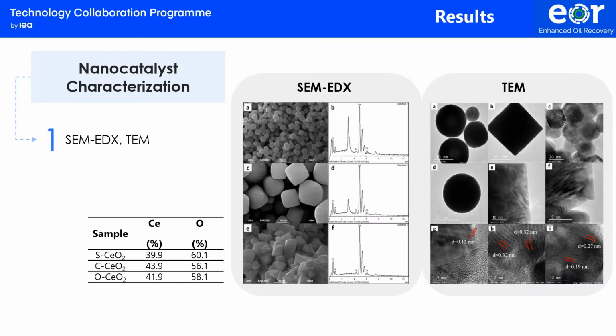As for the characterization of the nanoparticles, morphology and size were validated. The diameter of the spherical nanoparticles was observed as 14 nanometers with a rough surface. The cubic nanoparticles present cubes with a smooth surface and an average size between 14 and 16 nanometers. The orthorhombic shapes are observed with an average size of 20 nanometers, and the structures are highly agglomerated.